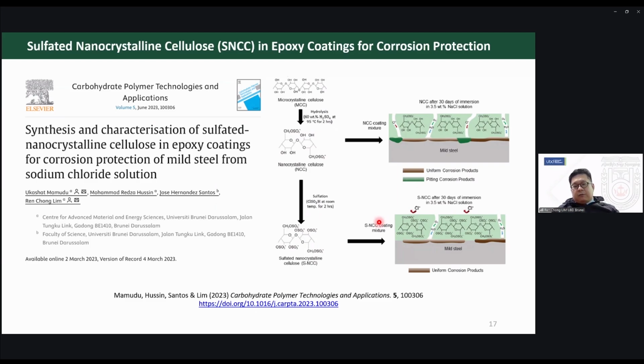In the maritime environment, we normally mimic it using a 3.5% sodium chloride solution, so the corrosive species is, in addition to the water, also the chloride ions. I'll say a few words later about why we are okay with the water, but more importantly we want the chloride ions to be blocked. We then hypothesized that introducing more of these sulfate groups will make the coating more negative, and that will help repel the chloride ions.